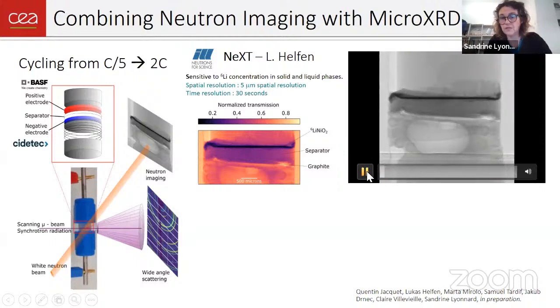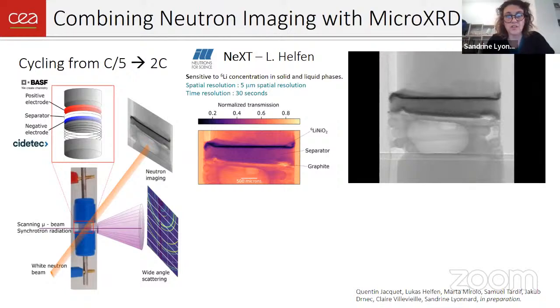And I'll play this for you. As you see, this is accelerated a bit with respect to real time. You really nicely see basically the lithium ions moving in the cycling battery. The time resolution is 30 seconds and the spatial resolution is 5 microns. So this is really good, but it gives you no indication on the phase transformations and what happens in the active materials.